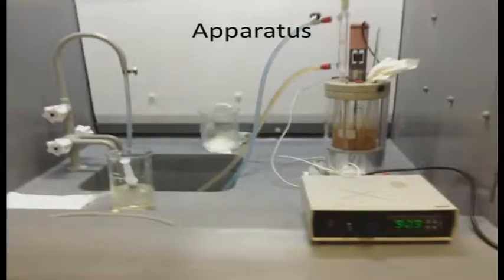So I kept the iron constant. These experiments weren't looking at that variable at the time. Temperature was varied. Leached over a range of temperatures from 25 up to 95 degrees, with 3 acid concentrations, 25 to 100 grams per litre sulfuric acid. These conditions were roughly based on another paper published last year. It was looking at an actual ore specimen from Russia. So leaching took place in this small reactor. It's just a 1 litre temperature controlled lab scale leaching reactor built locally.